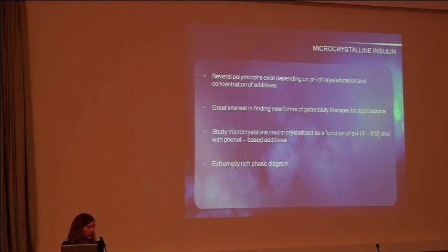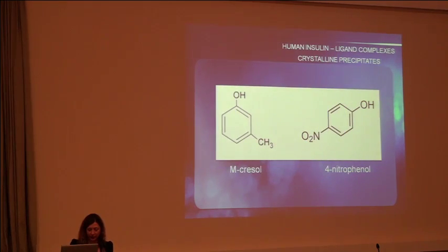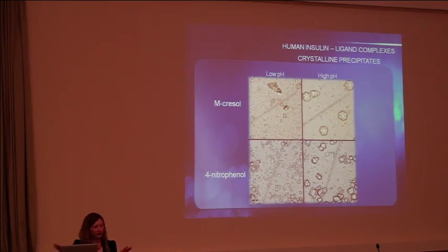So today we have discovered a very rich phase diagram. One example out of many corresponds to these two ligands, m-cresol and 4-nitrophenol. They look like phenol, but they're not the same. They form different hydrogen bond networks. By crystallizing them at different pHs, we saw immediately that at high pH, you can almost see the sixfold rotation axis, so we knew that up here we should have one of these three molecular polymorphs, T6, R6, or T3R3. At low pH though, we were getting repeatedly very low quality crystals.